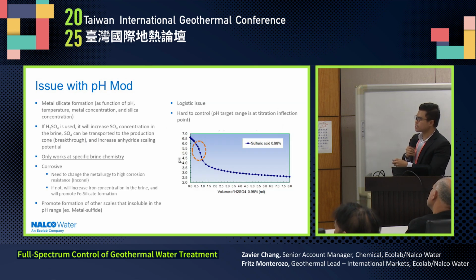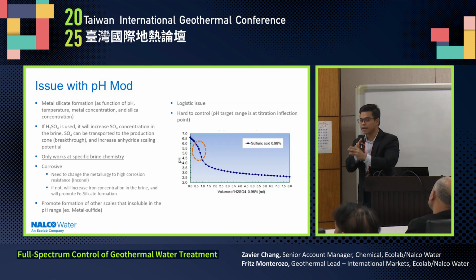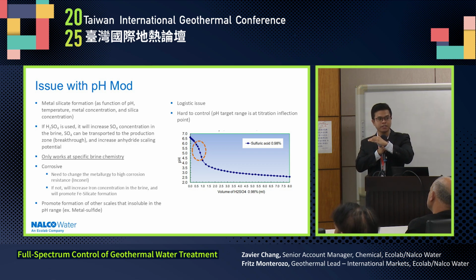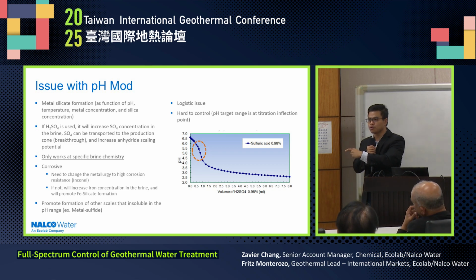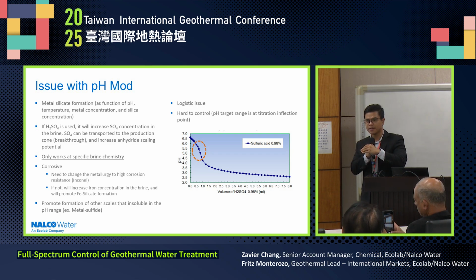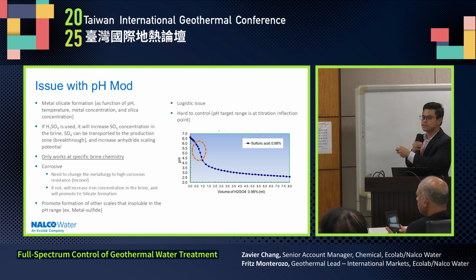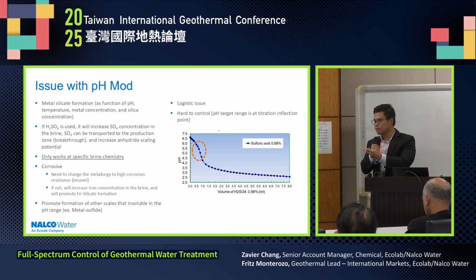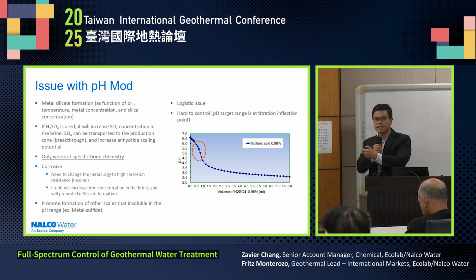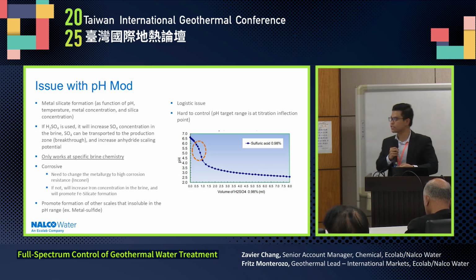But the challenge in acid treatment is you have a very small window. A slight addition of acid can shift your pH drastically. If you have too much acid, it contributes to corrosion. If you have less acid, it contributes to scaling. So you need to balance that out. We have seen in some treatment facilities doing pH mod that they tend to form metal silicates or iron silicates and iron sulfides. So you are possibly addressing silica, but you are creating another type of scale. That is the challenge for pH mod.